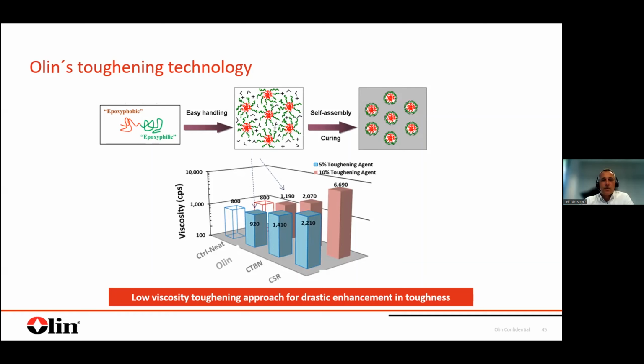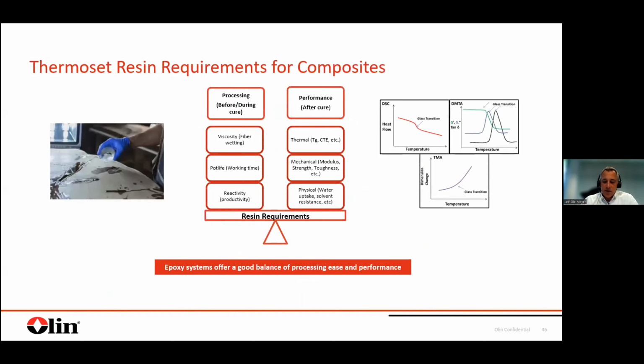So those liquid block copolymers are forming kind of particles inside the matrix, and these particles are responsible for the toughening effect. So it's really a low viscosity toughening approach, creating the benefit of toughening without negatively impacting the manufacturing requirements. And so in the end, this technology enables us to create a very good balance between the ease of processing and the performance of the tank with regards to certification, with regards to reliability and safety of the tanks.